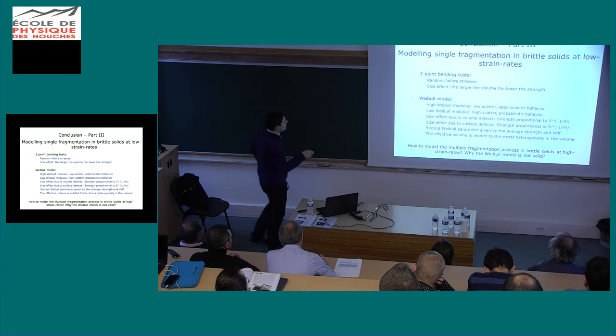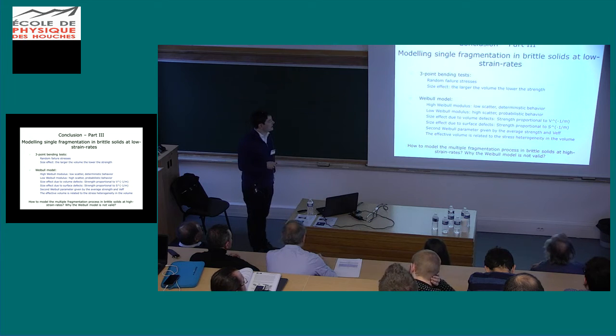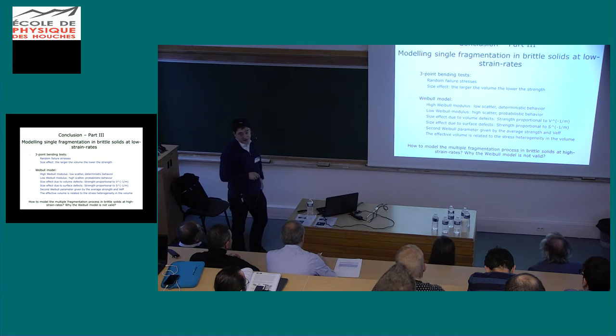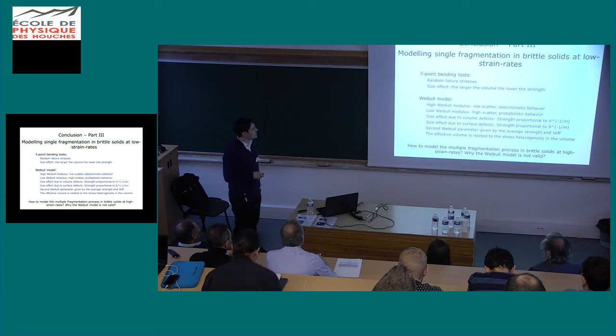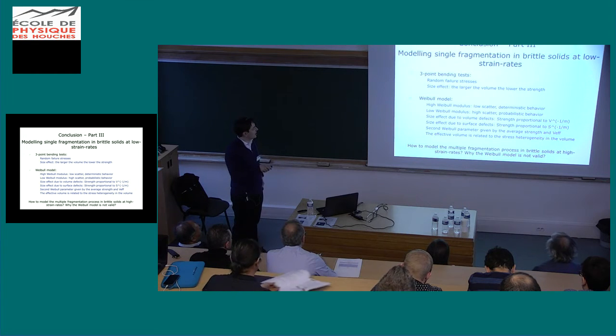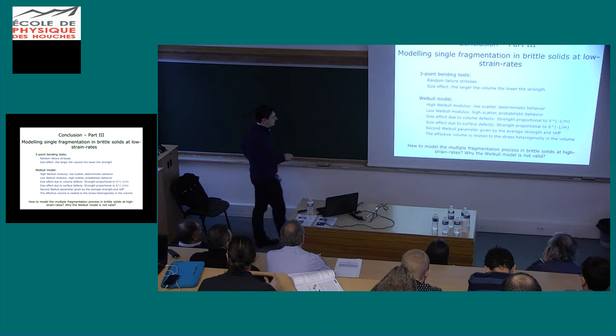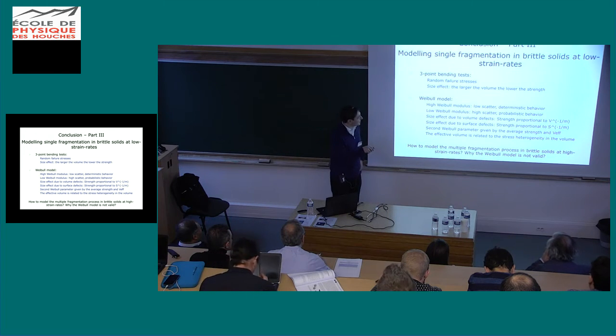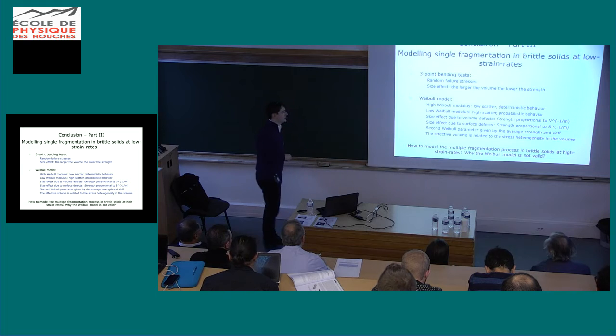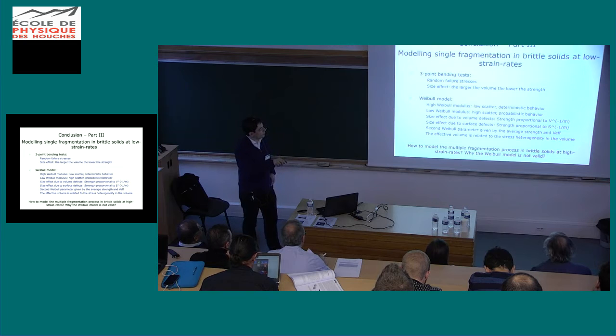Yes. So you can see that according to bending tests, failure stresses are random. Size effects are expected in quasi-static loading. The Weibull modulus indicates the scatter in the results. With a high Weibull modulus, you should have a deterministic behavior. Also, the predicted size effect is the following: it should be proportional to the volume to the power minus 1 over m. So it's a very interesting prediction of the model, because m was provided by one set of experiments.